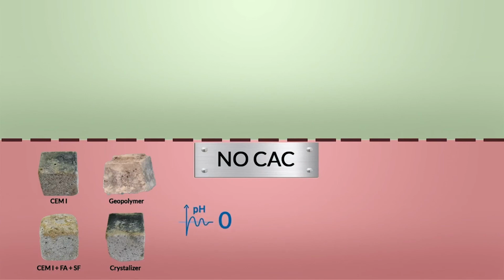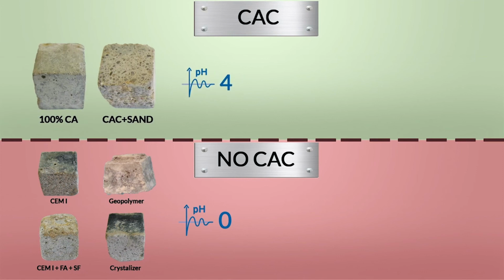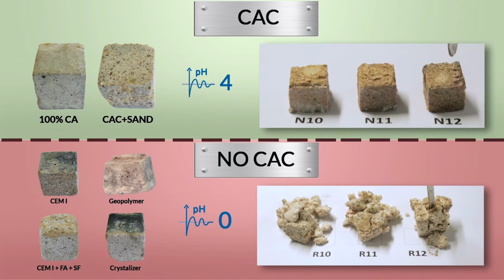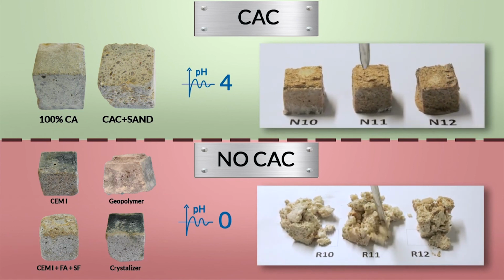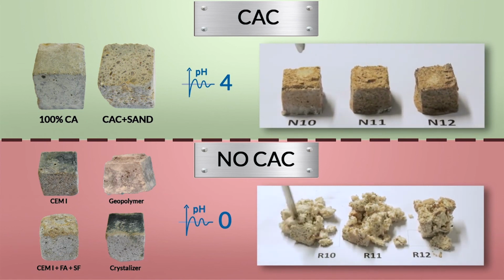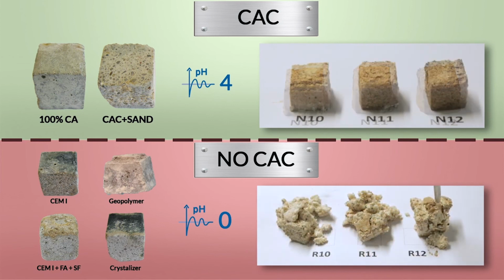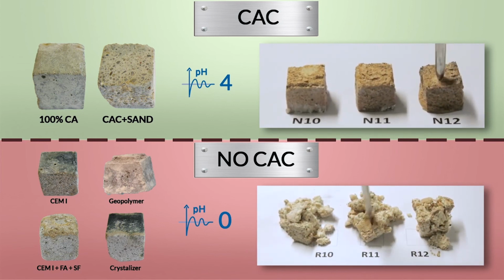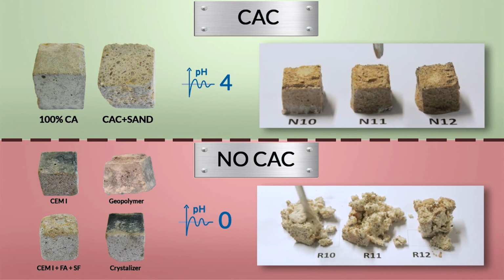The Fraunhofer test is an accelerated test to evaluate, within 1 year, the MIC resistance of various building materials and their capacity to resist severe H2S biogenic corrosion. The results presented here show that the corrosion rate of calcium aluminate concrete is 5 to 10 times lower than OPC concrete, even when it is enhanced with silica fume or pore blocker admixtures.